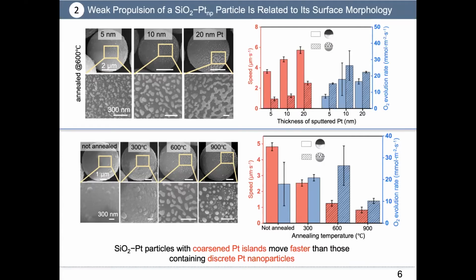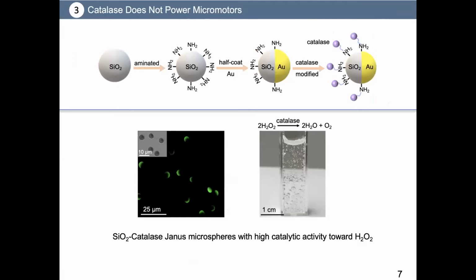And we found that silica platinum particles with coarsened platinum islands move faster than those containing discrete platinum nanoparticles. In addition, the poor propulsion of Janus microspheres described above is not limited to the material platinum, but also applies to any system involving the catalytic decomposition of hydrogen peroxide. So next we prepared silica catalase Janus microspheres, which could also rapidly convert hydrogen peroxide into water and oxygen.